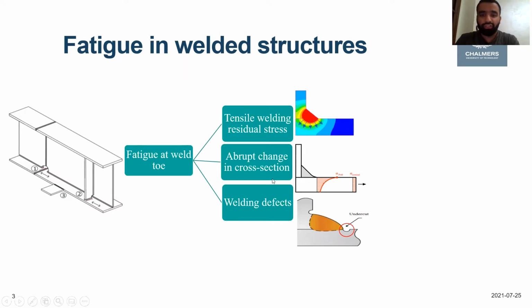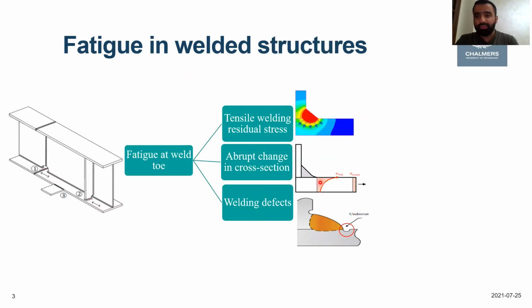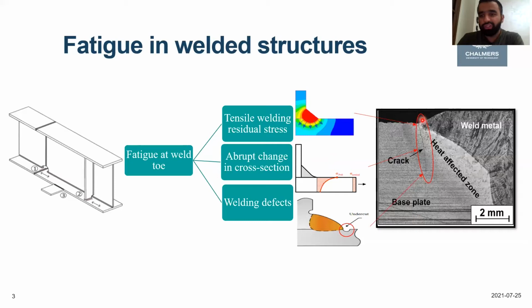Also because of the abrupt change in the stiffness, specifically at the weld toe, this causes stress magnification or localization at the weld toe, which magnifies the level of stresses here. Also because of the extreme heat that we're putting in the structure locally, we usually get some defects, and one of these defects exists in the same position at the weld toe. This, of course, aggravates the fatigue problem, and all of these factors cause a crack initiation, which develops to propagate through the plate thickness and finally causes fracture.